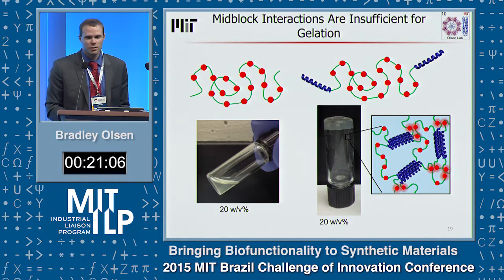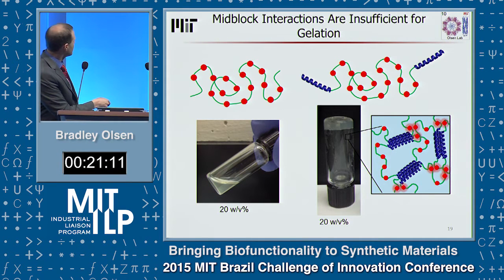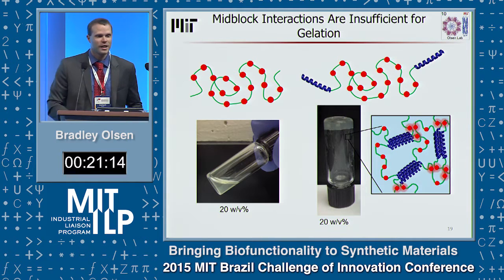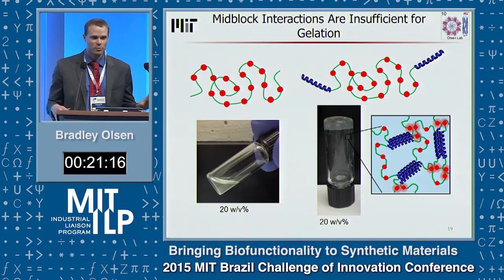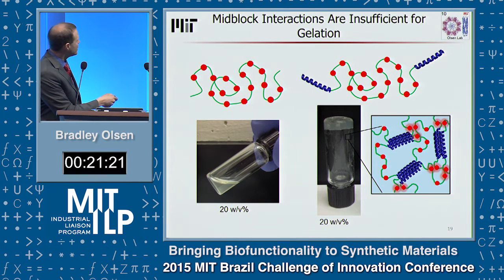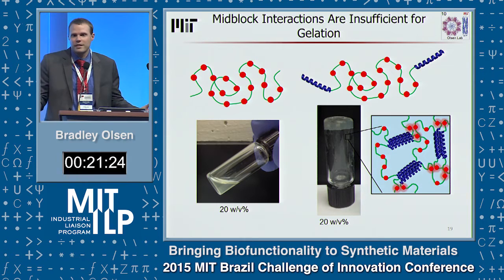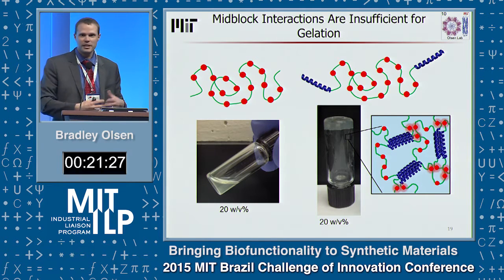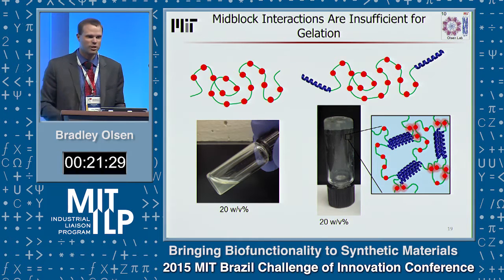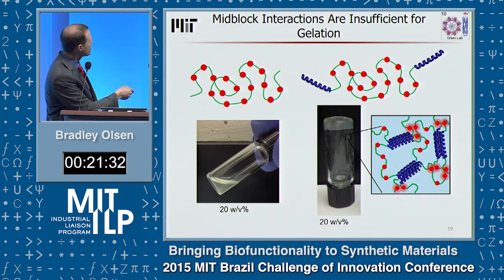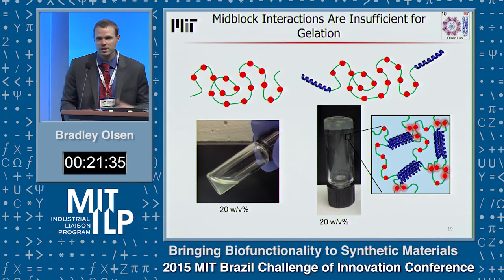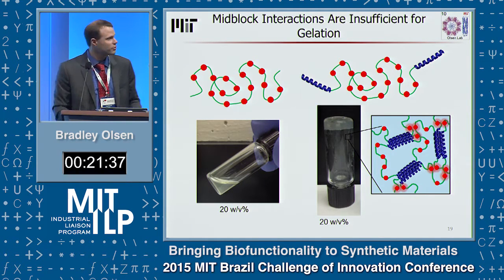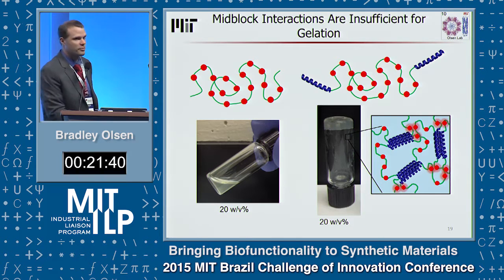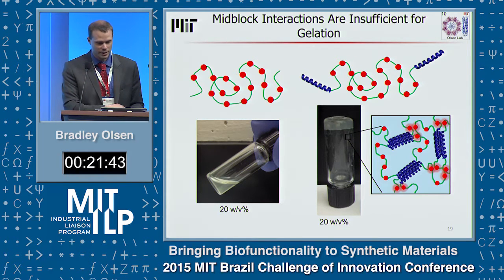And when we express this material recombinantly, we get a huge increase over the recombinant natural protein, but we get no gel. So the domain that we excluded from the protein is believed to be responsible for gelation. What we can do, just like in polymer engineering, is add in a cross-linking group. So now we take this and engineer it like a polymer engineer, like a material scientist, and add in a protein cross-linking group. Here we add an associating helix, but you can really add any sort of cross-linking group, and we've done several different ones. And you can now make this into a gel. So we can now replicate these gels in very high yield.